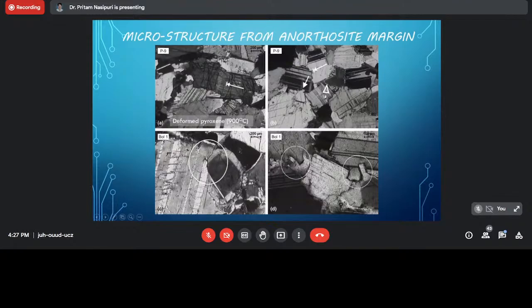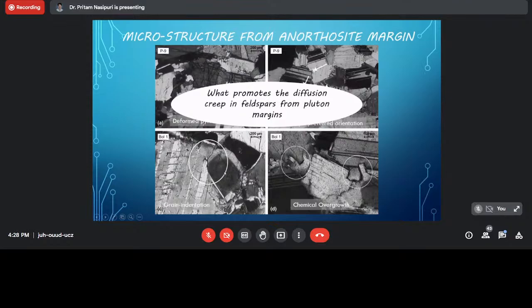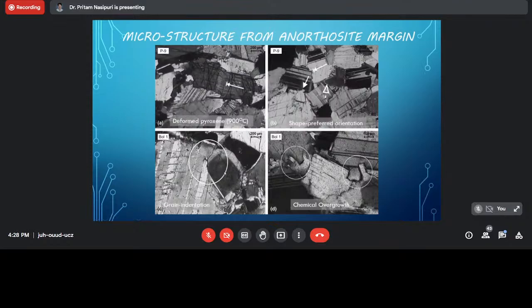Now, there was a third one, a grain indentation. One grain is included within the other grains. And finally, chemical overgrowth. These are the microphotographs, because at that time I did not have access to SEM. All these features indicate that the feldspars in the marginal part deformed via diffusion creep. And you can see the grain size is roughly 200 to 500 micrometers.